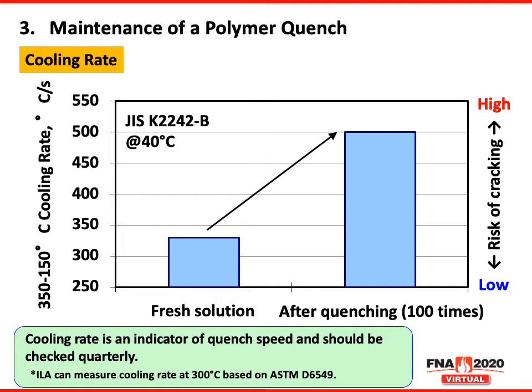Now, what does the cooling rate do? Well, as we talked about the cooling rate, you move that chart to the left. You move that cooling curve to the left as you used it. And you can see here that you go on a fresh solution from about 325 degrees per second to about 500 degrees per second after quench. What is happening there is your polymer is being thermally degraded through the heat generated in the heat treat process, and it's becoming mechanically sheared by going through the pump that recirculates the polymer quench.